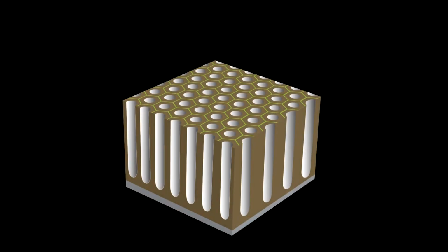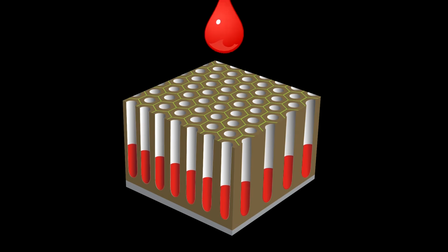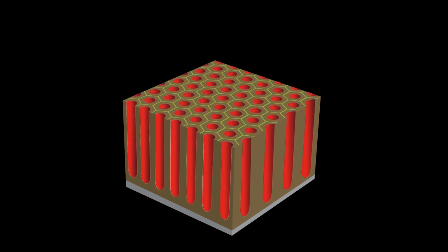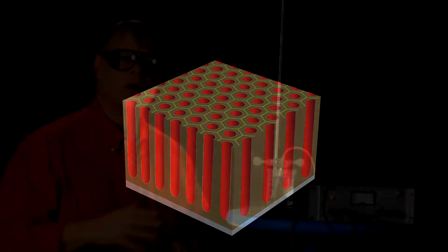The pores in this layer give the aluminum a unique characteristic important for a consumer device: the ability to be colored. The pores formed on the surface have a honeycomb pattern. Inside these layers, one can place dye of any color. Once the pores are filled, engineers seal the layer by boiling the aluminum in hot water. This closes the pores, locking the color in forever. You cannot scrape it off without removing the aluminum.